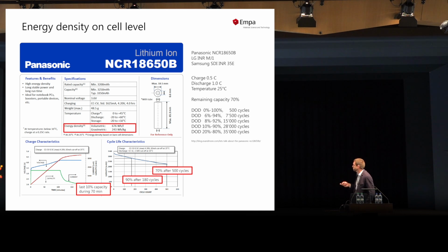Now, if you look a little more at the charge characteristics down here, you can see that the battery is first charged at constant current, so the capacity increases linearly. This takes a little bit less than 2 hours, but after 2 hours, the battery is put in constant voltage mode because you cannot exceed a certain voltage for safety reasons, and the battery is soaked for another 70 minutes, where you get another 10% of capacity, which is probably not always a very useful capacity for the application. But that's the way to get to this 243 watt-hours per kilogram. So if you subtract about the 10% of that extra capacity, you're back down to 220 watt-hours per kilogram.